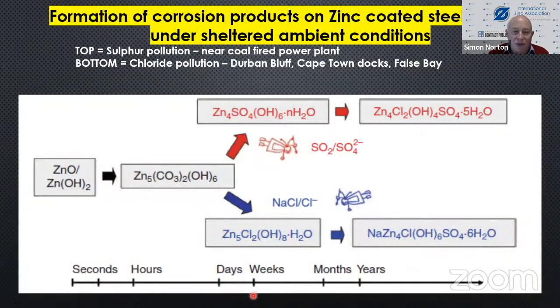So if you look at this brief little box model, you'll see that on the left-hand side, zinc oxide hydroxide is formed. The atmosphere then forms zinc carbonate hydroxide over a period that goes up to days and weeks. And then with time, if you were exposed to sulfur dioxide sulfates near the sea, or a power station or coal-fired power stations, you'll get these compounds. And if you were exposed only to the atmosphere at the sea, you'd get this compound sitting over here. And how you use this knowledge will determine how you design your structure, protect it, using what the other expert speakers are going to be talking about.